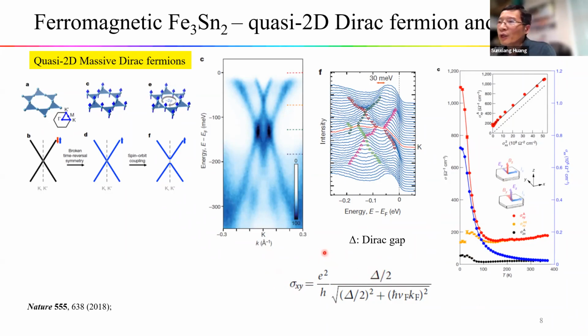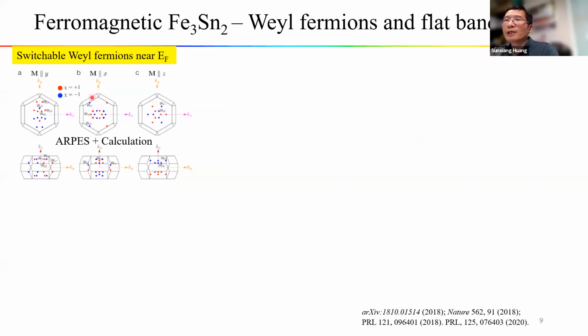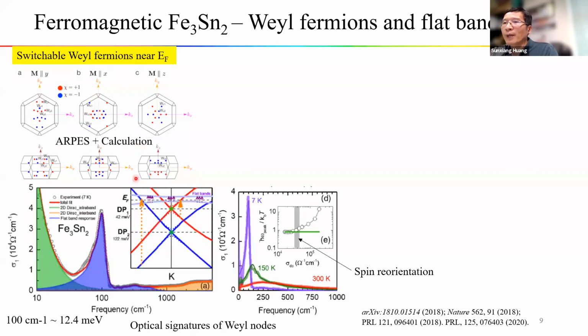But there are also some other results suggesting that in this material there are also Weyl fermions very close to the Fermi energy. So in this work, they did some DFT calculation and the ARPES measurement. So they suggest, very close to the Fermi energy, there are Weyl fermions whose configuration can be tuned by the direction of the magnetism. So this scenario is further supported by the optical measurement on these materials.